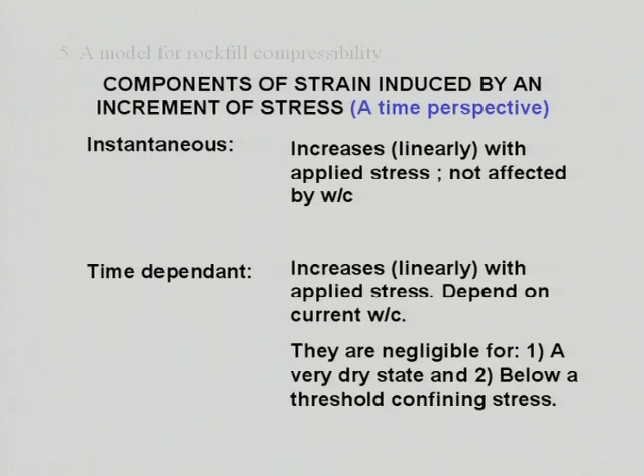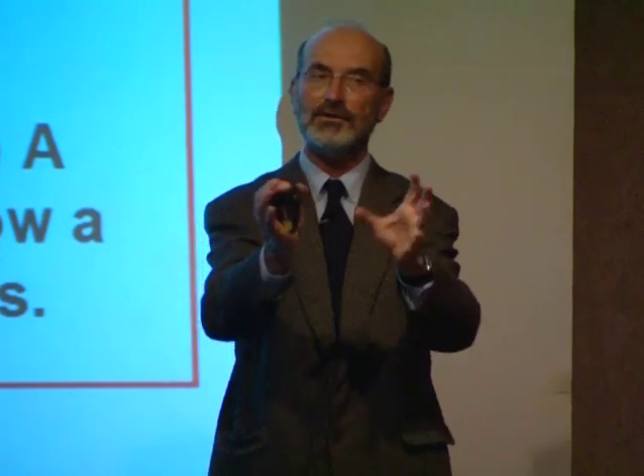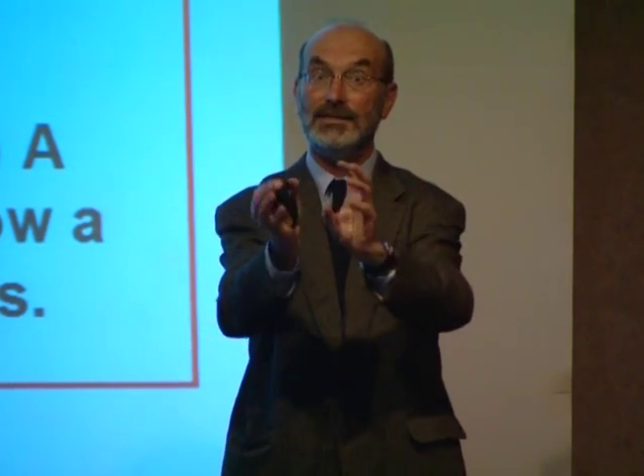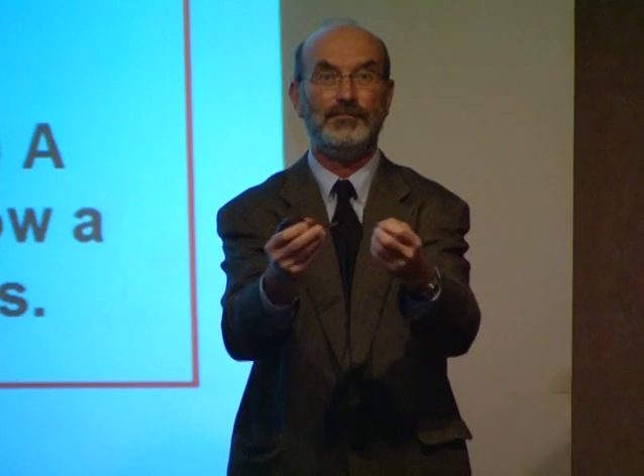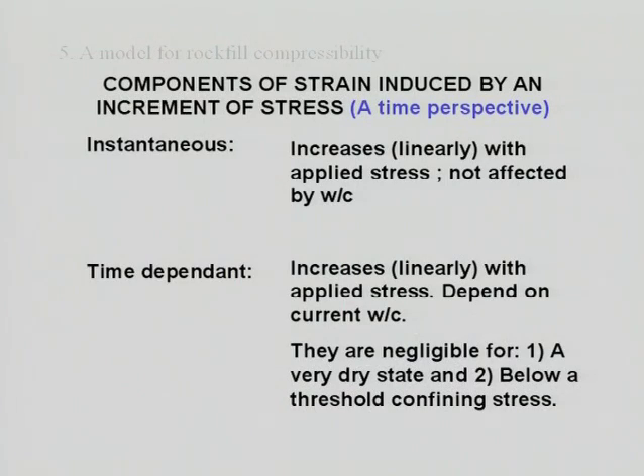Now, from this perspective, I call it the time perspective here. The instantaneous deformations, and I don't have time here to explain the details, we realize that they increase linearly with applied stress. But what is perhaps more important is that they are not affected by water content. And probably this is what you would expect, that if you rearrange some structure in a rockfill, water content is not important at that time, because this is a purely kinematical type of problem.